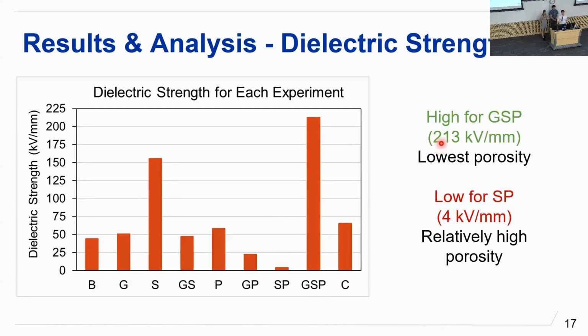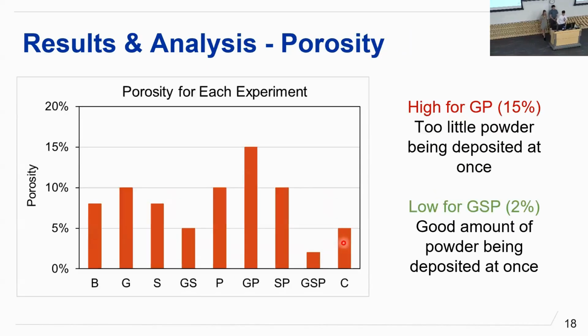And we attribute this to a low porosity because porosity and dielectric strength have an inverse relationship. And finally, we have a very low value of dielectric strength for experiment SP, which is experiment 7, which had a high stage speed and high number of passes. And we attribute this to a high level of porosity for the same inverse relationship.